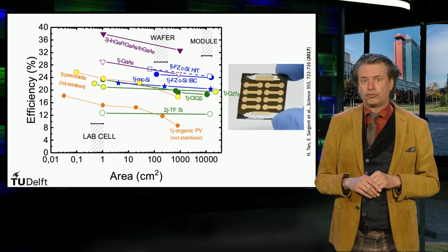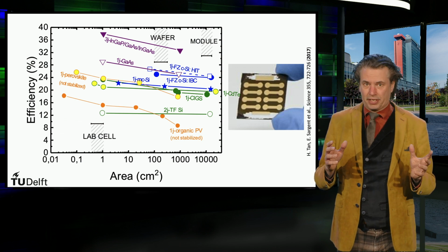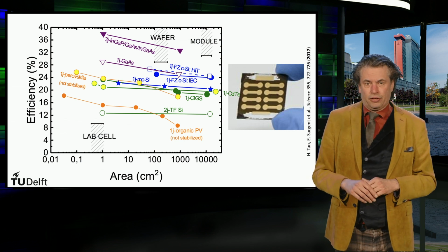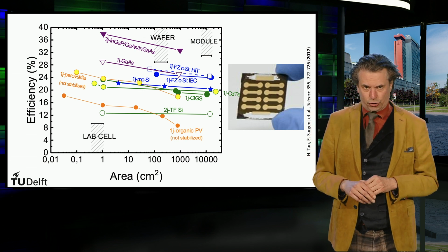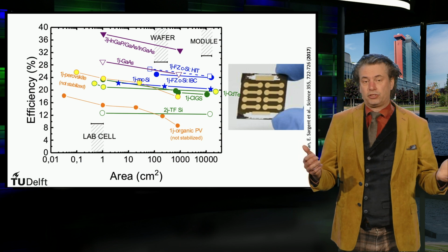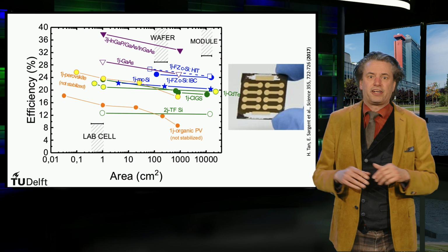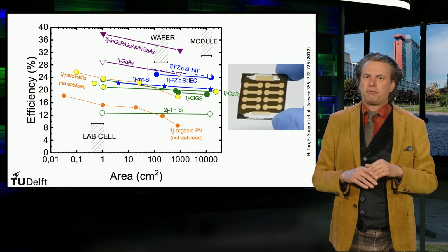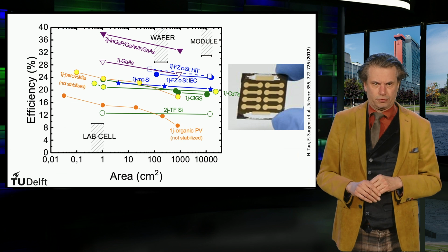Best efficiencies for an 800 square centimeter module are 17.9%. Note that the perovskite technology also suffers from instability issues. The performance degrades in time. So perovskite PV technology still faces significant challenges to prove that it can become a mature technology to be commercialized.